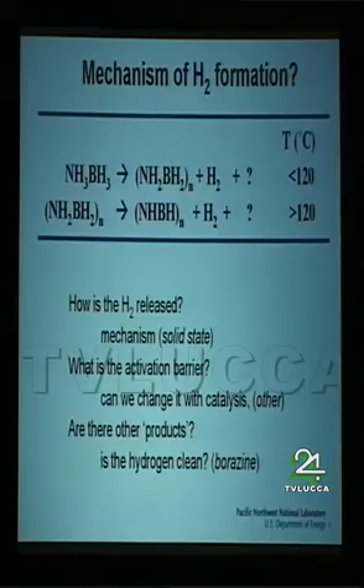It's a solid state reaction. It melts at 114 degrees, and it loses hydrogen quite vigorously at those temperatures. But you can release it from the solid state at temperatures as low as 70 degrees if you're patient, I guess. Or if you put it in a scaffold, things come off a lot faster. We wanted to get quantitative about this to know what the activation barrier is. So this is when we were doing some of our comparisons.